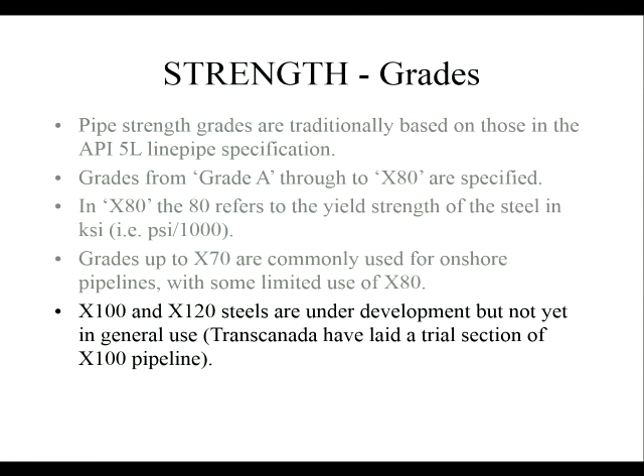As I said, X100 and X120 steels do exist. You can make them, but they're more expensive because they're a bit more highly alloyed, and nobody uses them yet, though TransCanada have been trying them out. There are various reasons why you might. If you were in a very cold country, if you can modify the steel specifically for its ductile brittle transition behaviour, you might want to do that more than spend the extra installation money dealing with heavier pipes. Because if you've got a higher grade steel, the wall thickness of the pipe will be smaller and they're easier to transport. Some people like that as a way of doing it if you've got to transport over hard to run terrain.